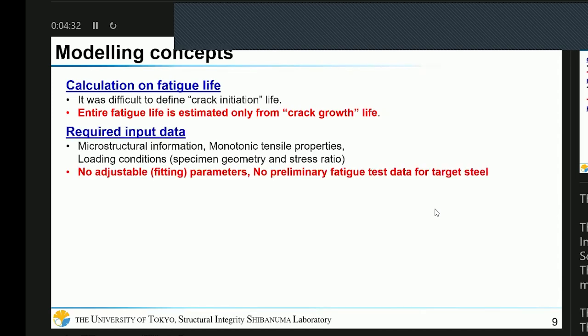And the second one is the required input data. As I mentioned in the introduction part, the microstructure information, monotonic tensile properties, and loading condition should be dominant factors to determine the fatigue life. So we use this information as the input data. And we don't use any adjustable fitting parameters. And we don't need any preliminary fatigue test data of the target steel. So it means we provide a pure prediction.